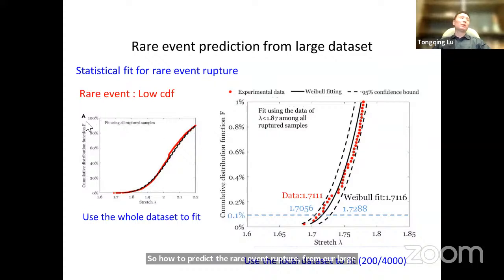So because we plotted a CDF as a function of stretch, a rare event just means low CDF, because CDF just means fraction. So here the fraction is 20%. Here, for example, at 1.7 something, the CDF can be very low. So this is the rare event rupture stretch. If we zoom this out, the right figure is just a zoom out. The vertical axis goes up to 1%. So this is a rare event region.